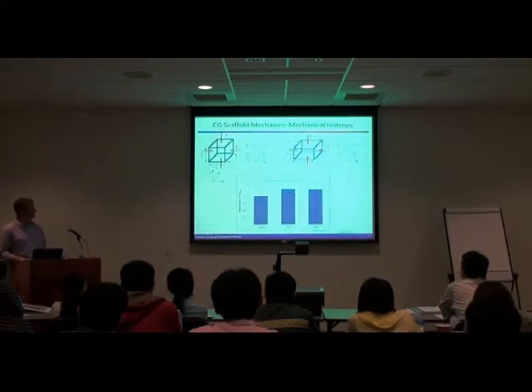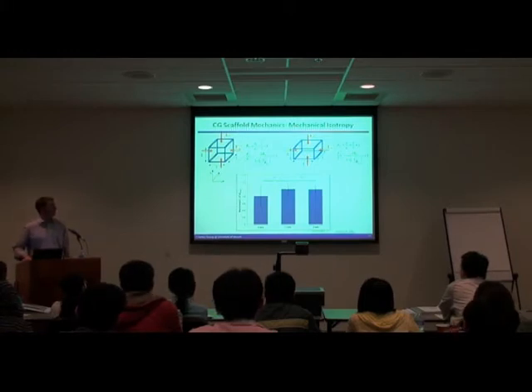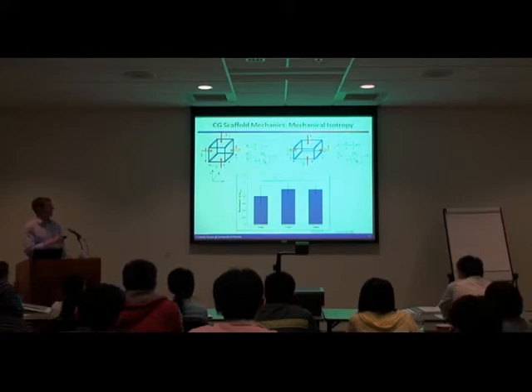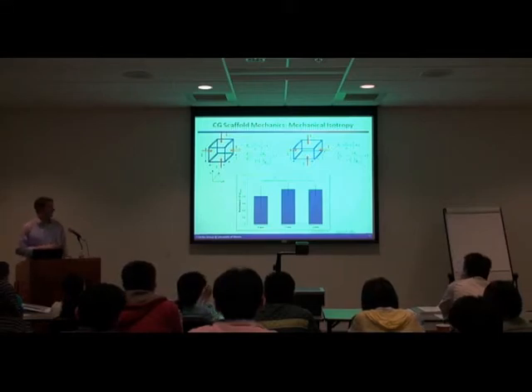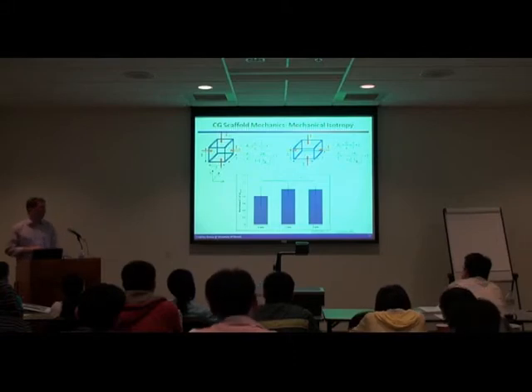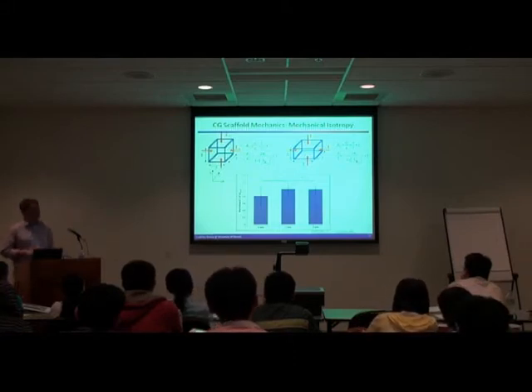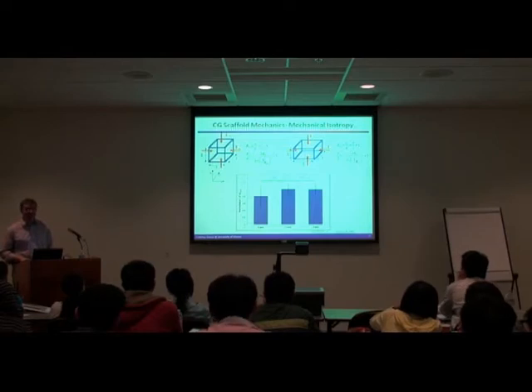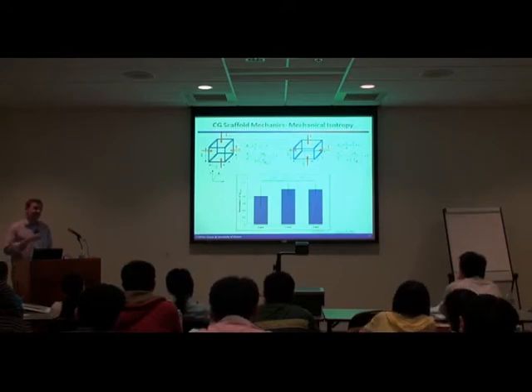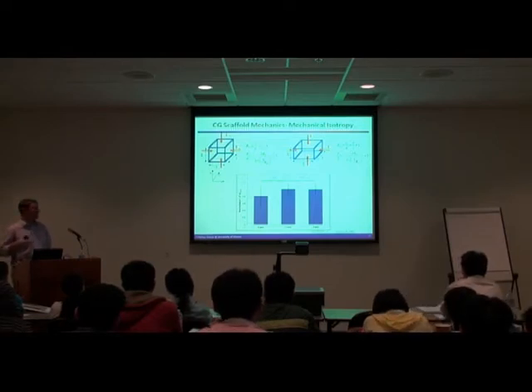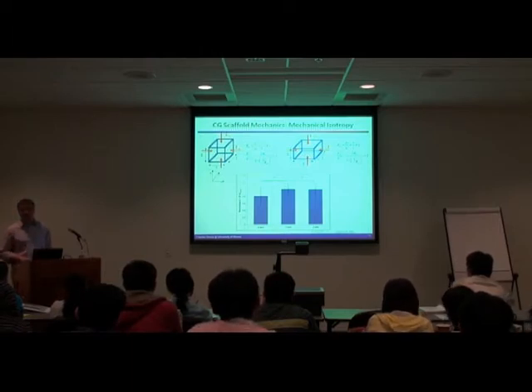So there are other ways in which you can integrate cellular solids modeling theory into your biomaterials. Another one is to look at the relative amount of isotropy or anisotropy of your material, depending on whether you have a relatively isotropic unit cell versus a highly anisotropic unit cell. The relationship in elastic modulus in orthogonal directions would be different. And so we found that for isotropic materials we make, there's no difference in elastic moduli across all three axes, and for some anisotropic materials we make, there's a very significant difference. And it's one that, again, you can predict. So what I'm trying to harp on here is that we're trying to build a biomaterial system within the concept of having a modeling framework that can describe it.